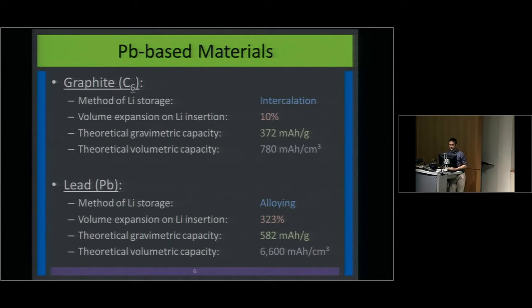This leads to a massive volume change, though. When you insert the lithium, the particle goes from one size to a size 323% larger, and this has its own set of issues. But because you can insert so many lithiums, you get a much higher capacity of about 582 milliamp-hours per gram. And because lead is so dense, your volumetric capacity is actually more than 8 times higher than that of graphite.